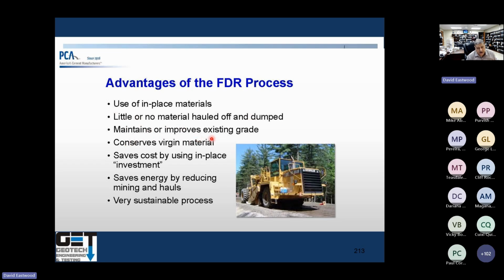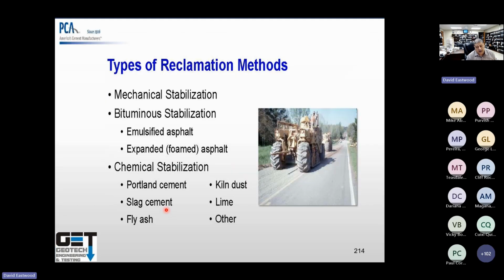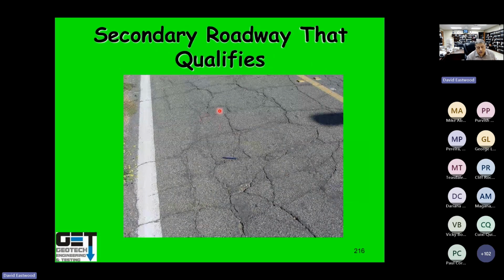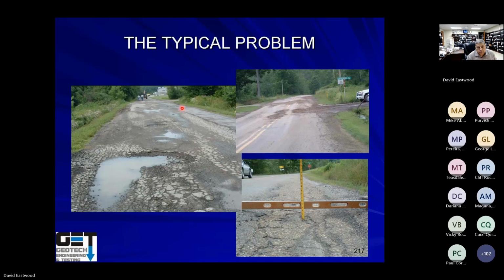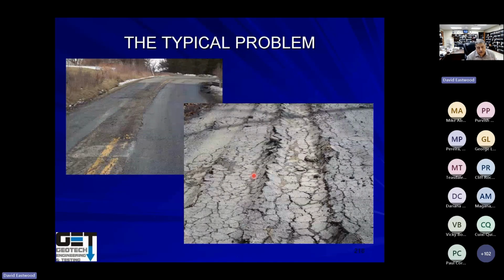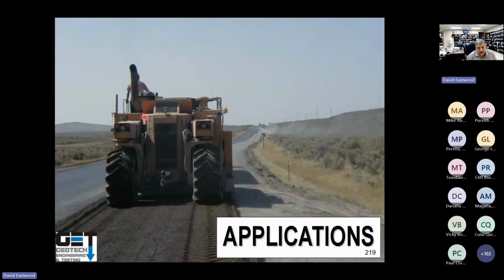It maintains or improves an existing grade, conserves virgin material that's already in place, saves costs by using in-place investment, saves energy, and is a very sustainable process. For the kind of stabilization, once you mix the material, you can use emulsified asphalt or foamed asphalt, or you can use cement. In this case, we recommended using cement. These are some of the pavements that may require full depth reclamation, or if your traffic loading is going to be high and the existing pavement cannot handle it, you got to use full depth reclamation.